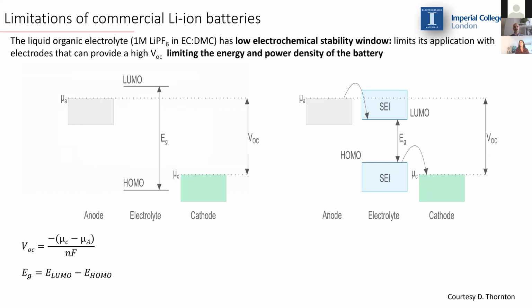There are 2 main limitations of this liquid organic electrolyte. One of them is the fact that it has a very low electrochemical stability window. The electrochemical stability window of the electrolyte limits the application of electrodes that can provide high cell voltage to the cell, which also limits the energy and power density that we can get from a battery.